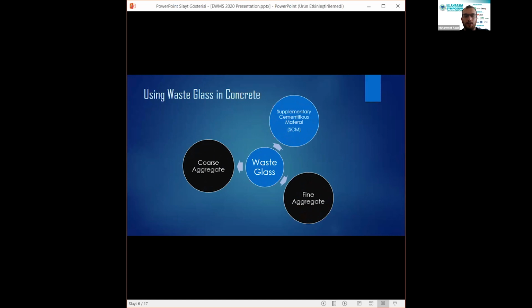Using waste glass for partial replacement of coarse aggregate was studied decades ago in the 1970s. Even if it has some benefits such as reducing unit weight of concrete, there are some concerns about its sensitivity to alkali silica reaction. What is alkali silica reaction? Alkali silica reaction causes cracks upon expansion. These cracks look like a honeycomb on the surface of concrete, and alkali silica reaction weakens the concrete and shortens its service life.